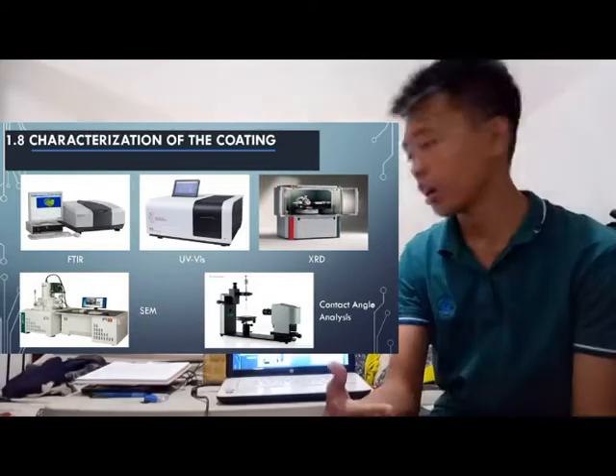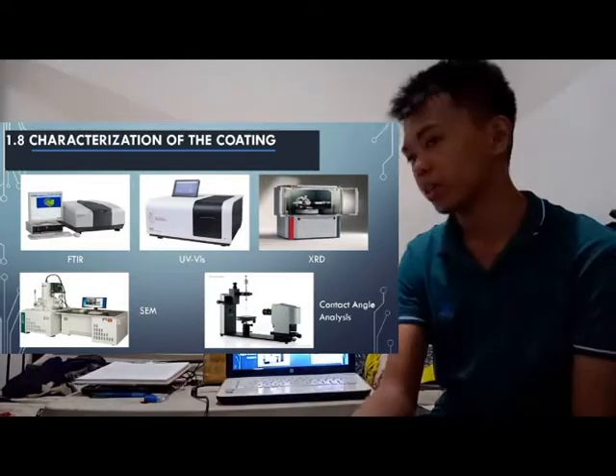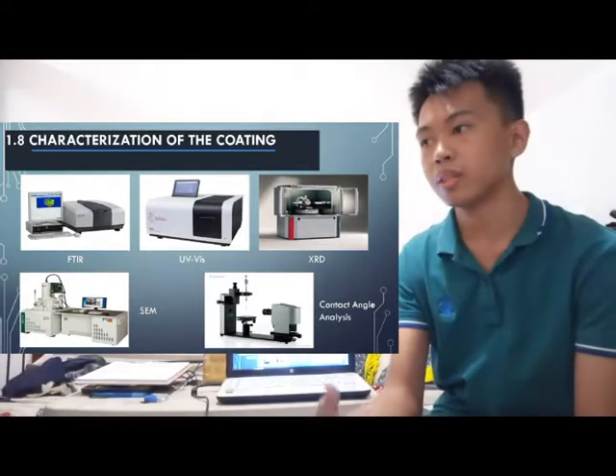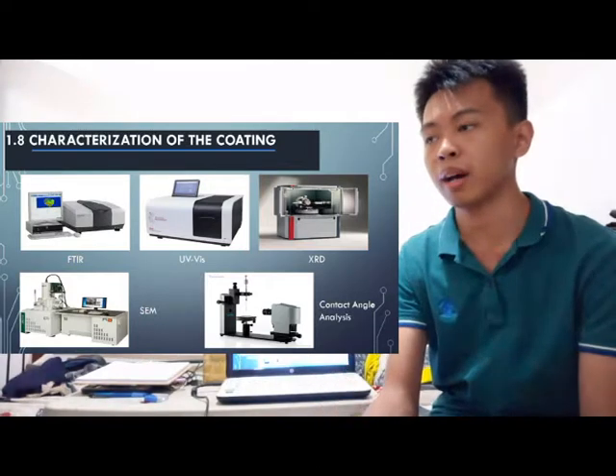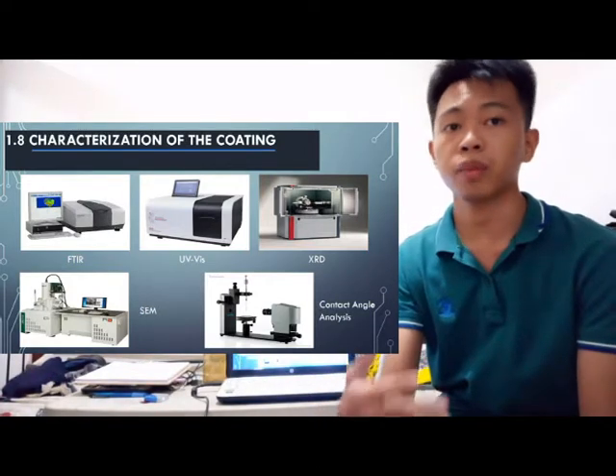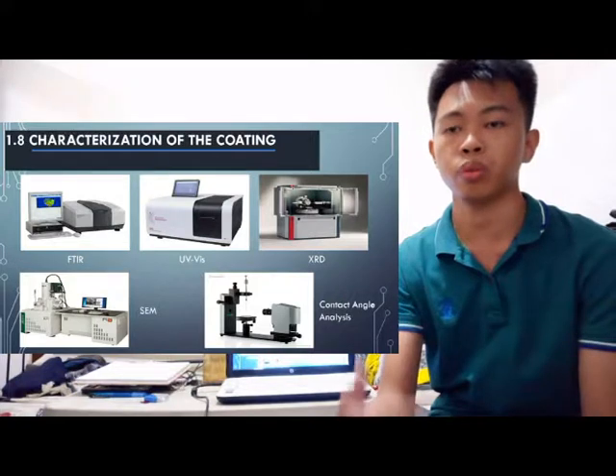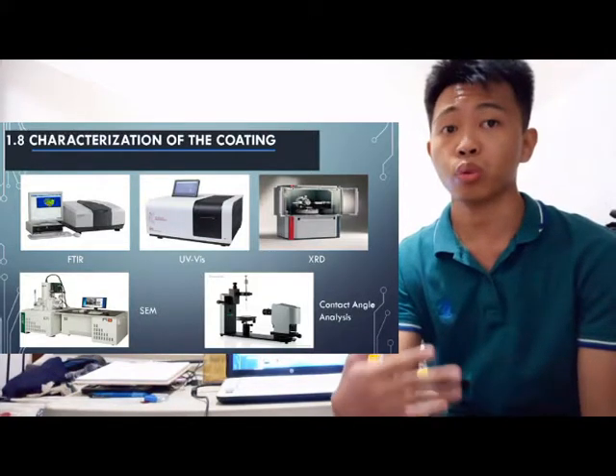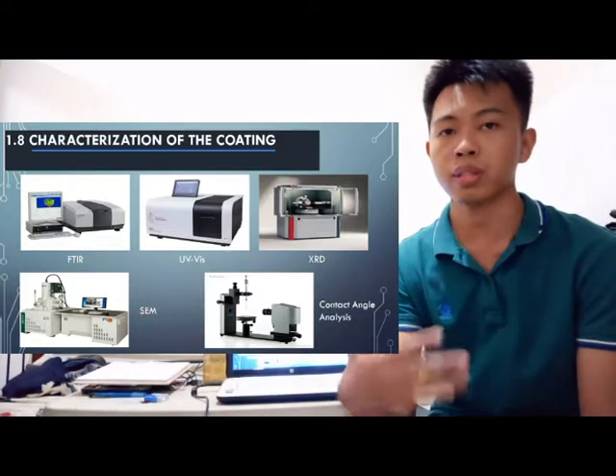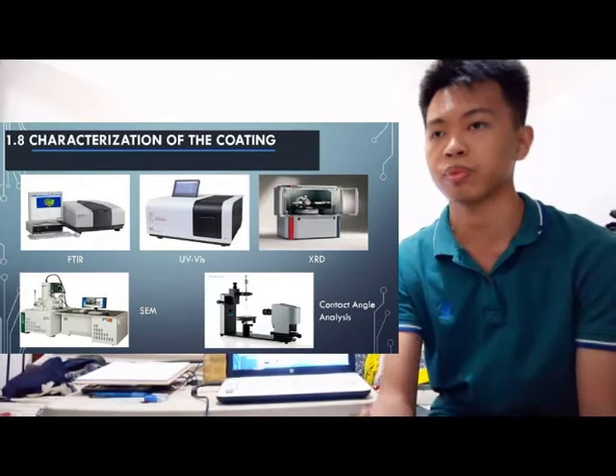for the FTIR, UV-Vis, and XRD, these methods will determine the chemical composition and structure of our coating. They will also determine whether the coating is present on the stainless steel substrate.